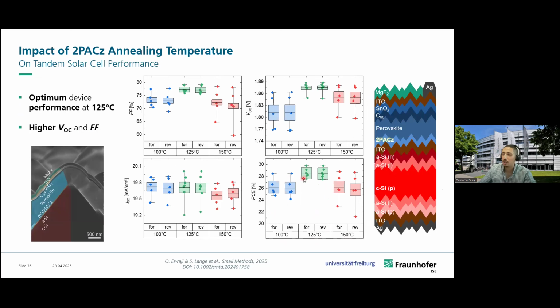And so here the solution that we came up with, or the hypothesis that we came up with, is maybe we can try to wet chemically deposit on top of the urea modified perovskite. We can solution process a certain solution that has a robust ligand, and the solvent can already wash away the urea from the surface and replace it with this robust ligand that can act as a passivation between the perovskite and C60.